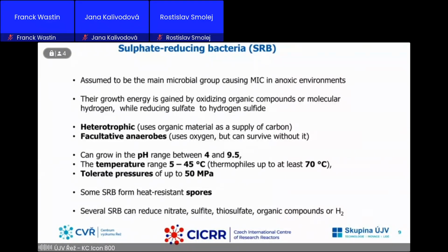So sulfate-reducing bacteria are assumed to be the main microbial group causing microbial corrosion in anoxic environments. They are heterotrophic, facultative anaerobes. They can grow in a pH range between 4 and 9.5. The typical temperature range for growth is from 5 to 45 degrees Celsius, but thermophilic sulfate-reducing bacteria also exist that grow at up to at least 70 degrees Celsius. Some sulfate-reducing bacteria form heat-resistant spores. That means they can survive in dry environments.